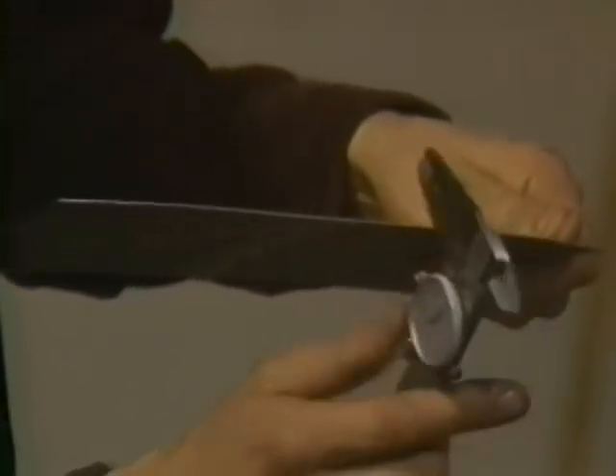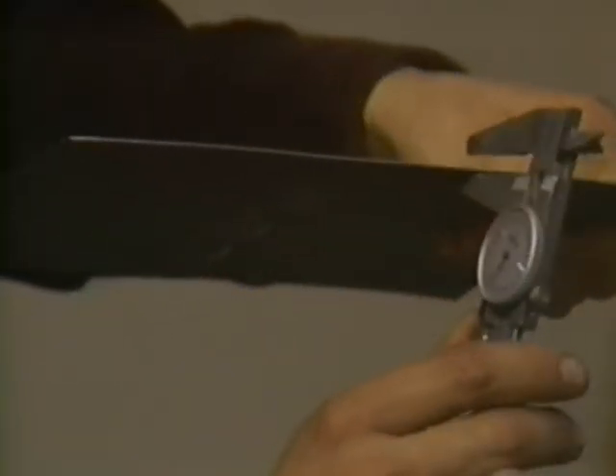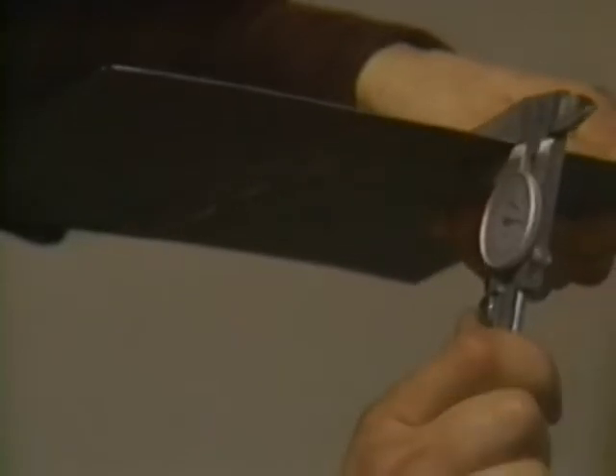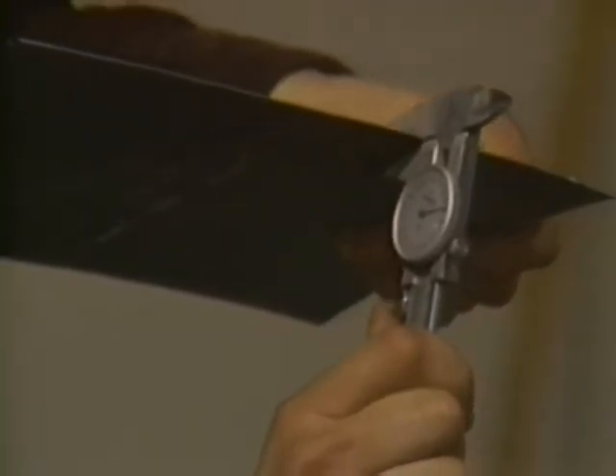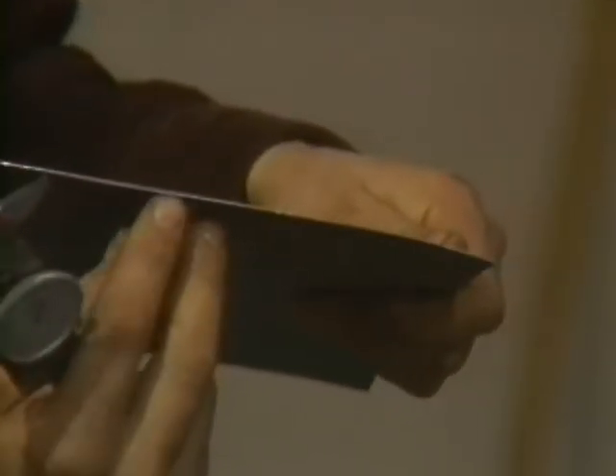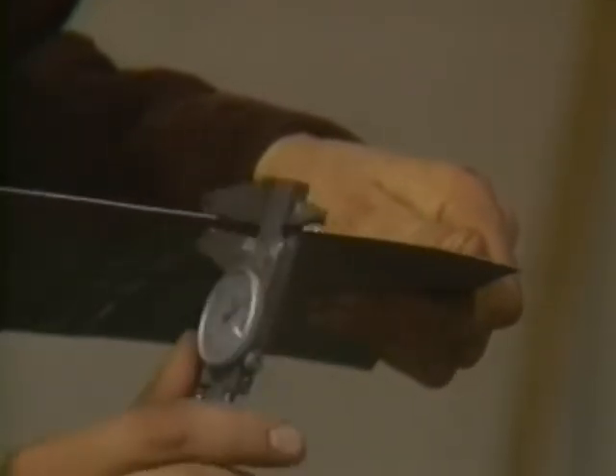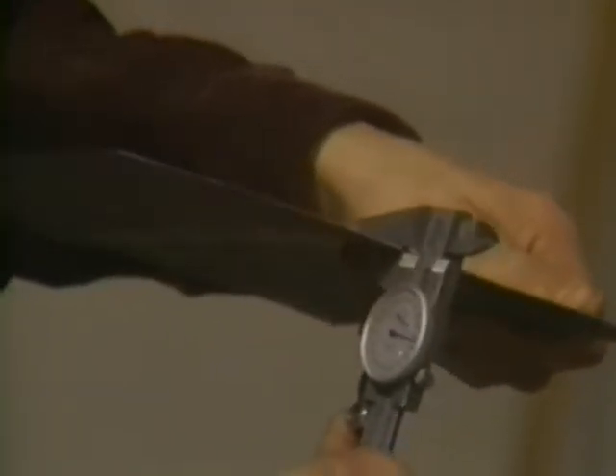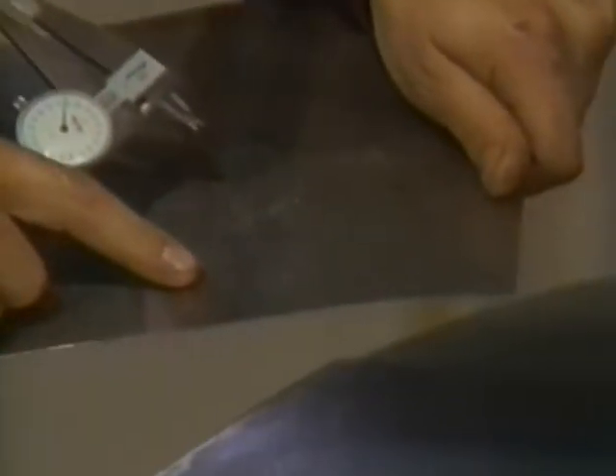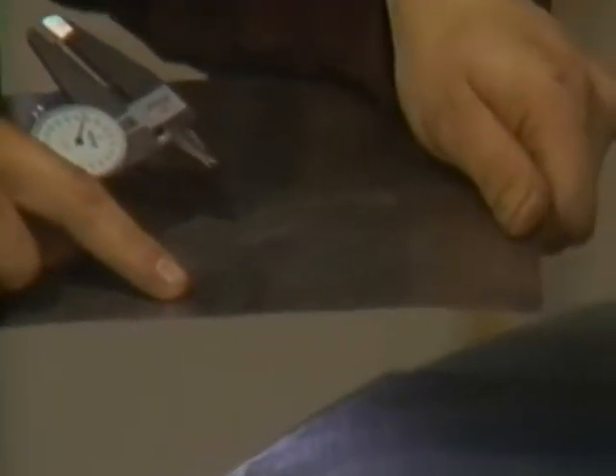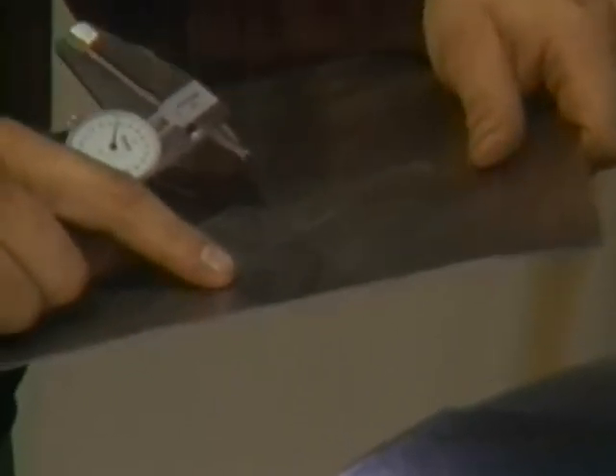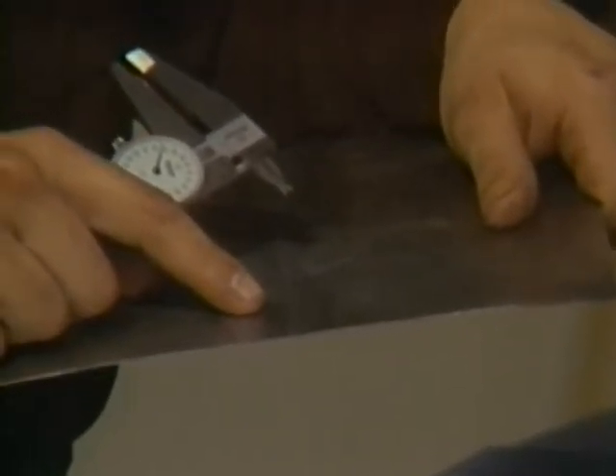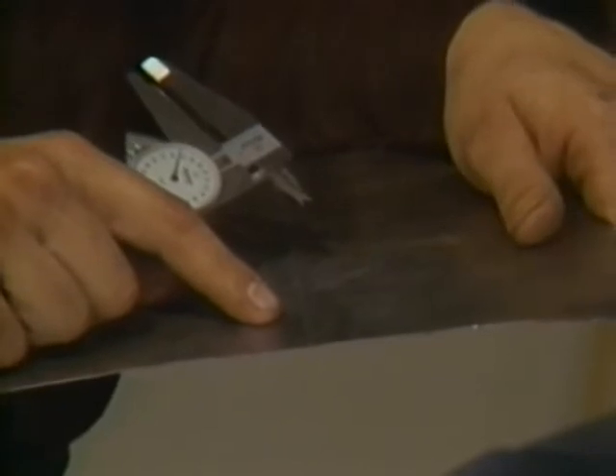The thickness, using a pair of dial calipers, of the sheet metal panel is 38 thousandths. The thickness of the weld where I fuse welded it and hammered it reads 36 thousandths of an inch. That's 2 thousandths of an inch difference in thickness. I find it's just as strong as using a filler rod, and it's a heck of a lot easier.